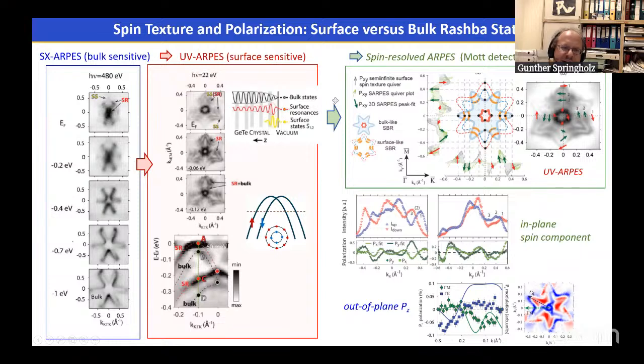So it is quite a tricky thing to separate the bulk contributions and the surface contributions, and the surface states also show a strong Rashba splitting, as it turns out. And then one can measure here the spin polarization along certain cross sections of this map.